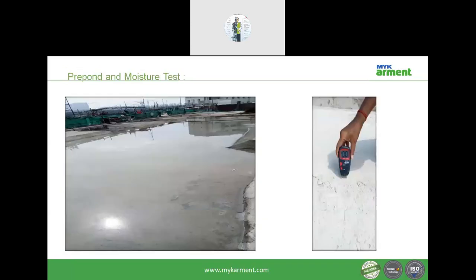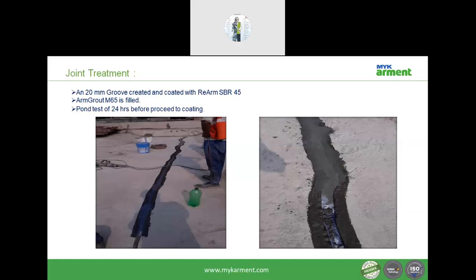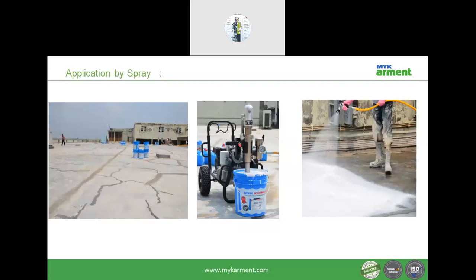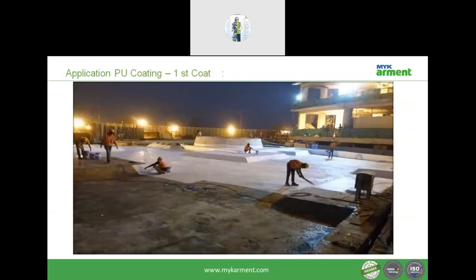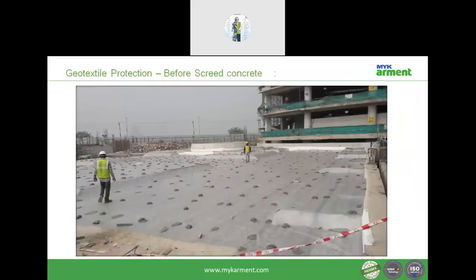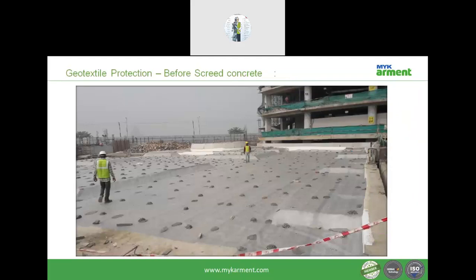Now, in a podium or a terrace, you need to pre-pond the surface and test for any cracks or seepage. Then you need to go for pressure grouting or an intervention. Check the moisture. When the moisture is less than 5%, then you can apply the polyurethane based systems. And this is the primer application, and you need to sprinkle sand, which gives a mechanical bonding, and you can spray or even use a roller to apply our polyurethane based coatings. You can apply the first coat, and then leave it for at least 8 hours for the second coat application. Once it is laid, to lay a concrete above the polyurethane, you need to use a geotextile, which acts as a layer that protects against any damage during the concreting process.